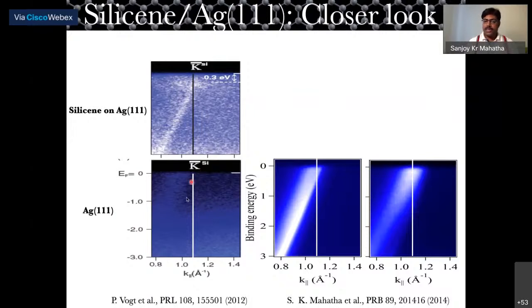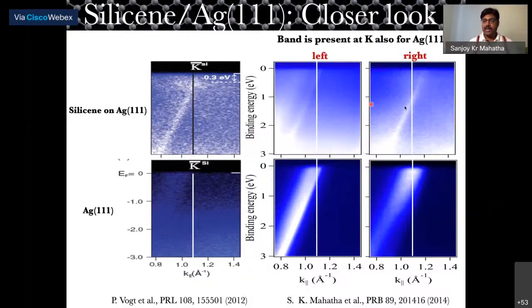So there must be something wrong. After putting silicon, what we found is that on the left and the right side of the detector, we could always see this kind of linear band crossing the Fermi level, and they are nothing but silver bands. So this is just the silver band we are seeing here after putting silicon, and that should not be a silicene band.